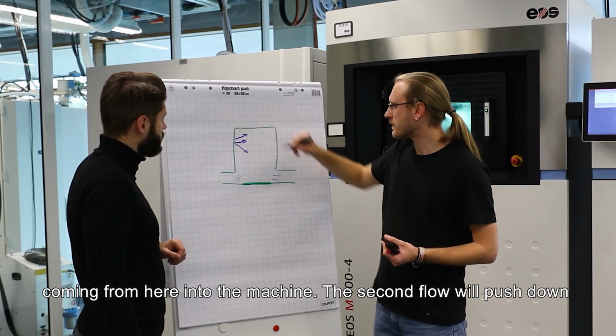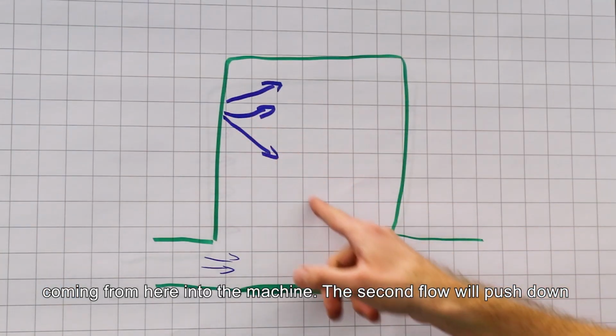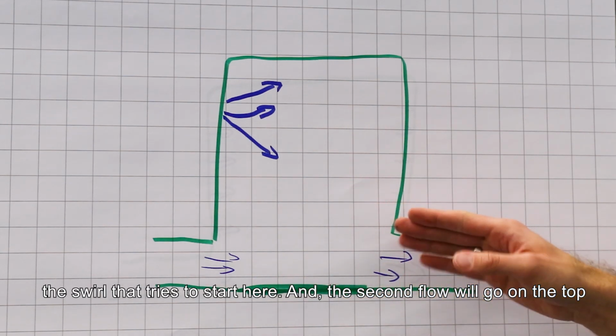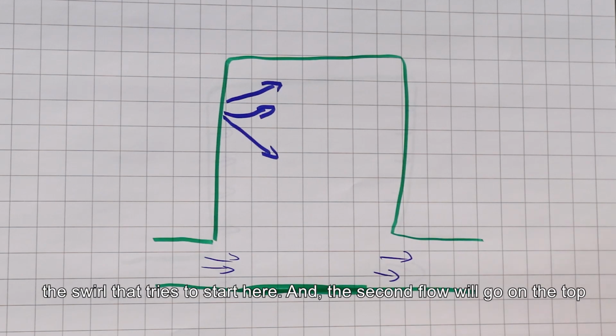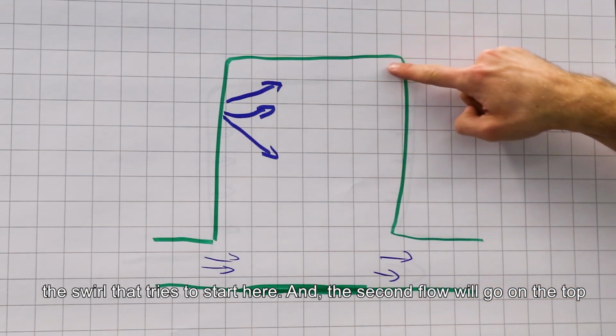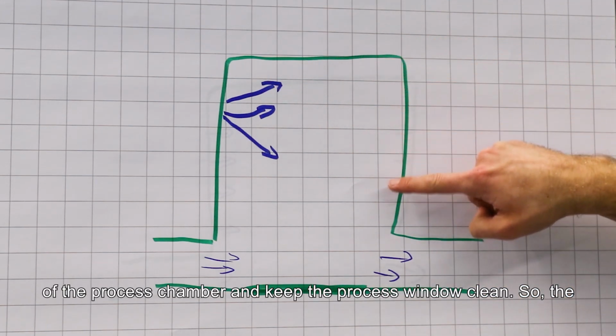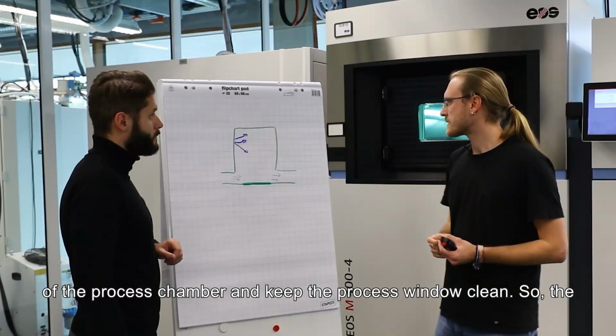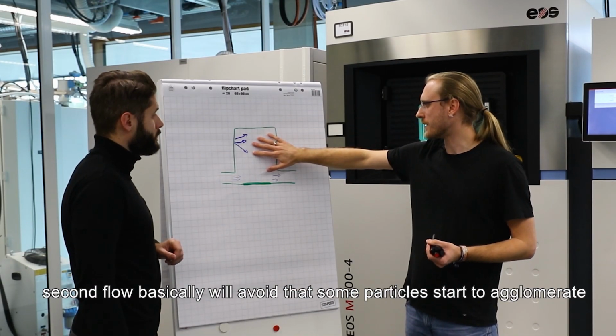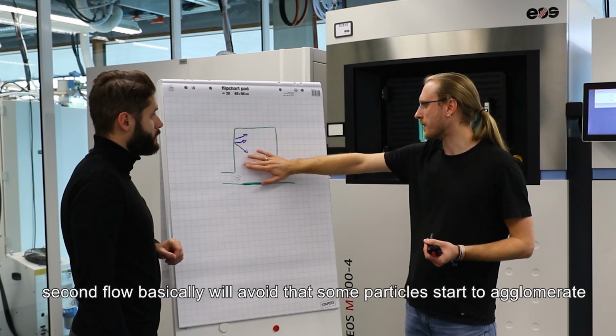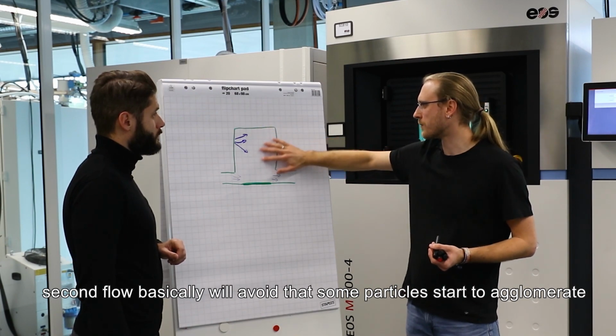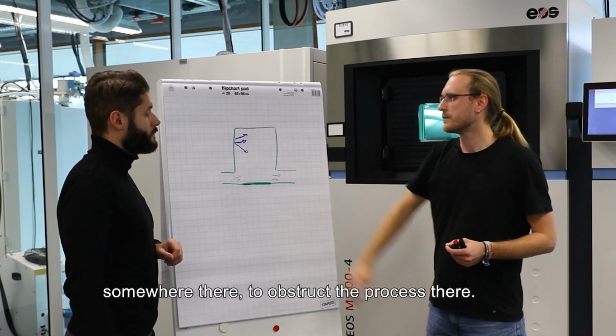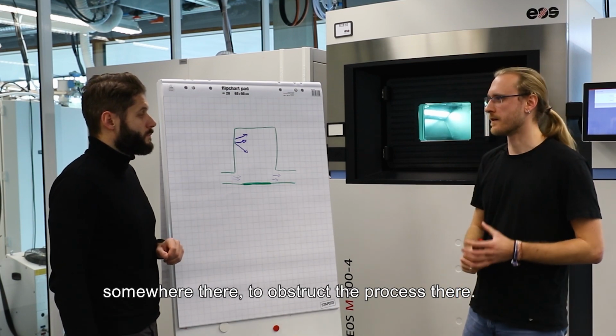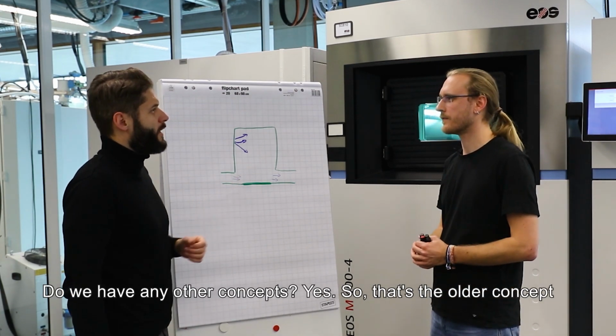into the machine, and the second flow will push down the swirl that tries to start here. And also this second flow will go on the top of the process chamber and keep the process window clean. So the second flow basically will avoid that some particles start to agglomerate somewhere there and obstruct our process there. Okay. Do we have any other concepts?